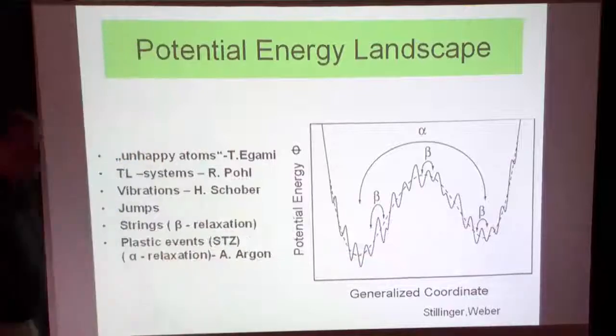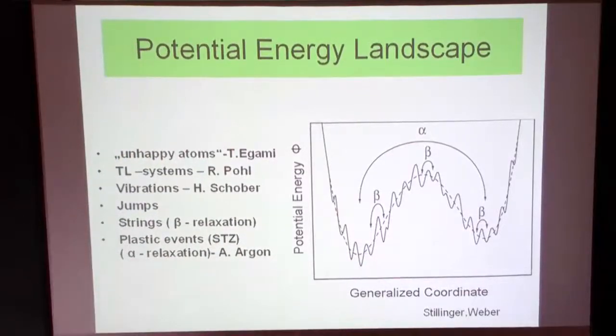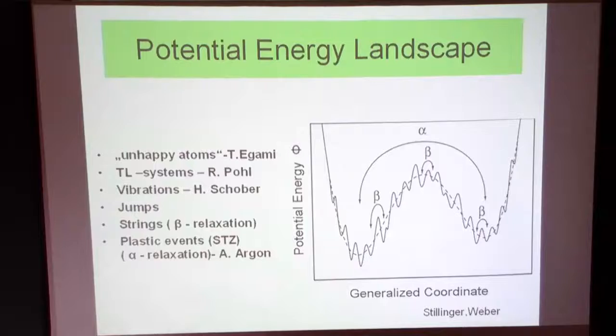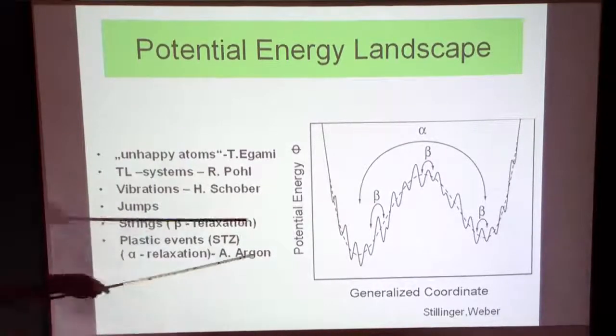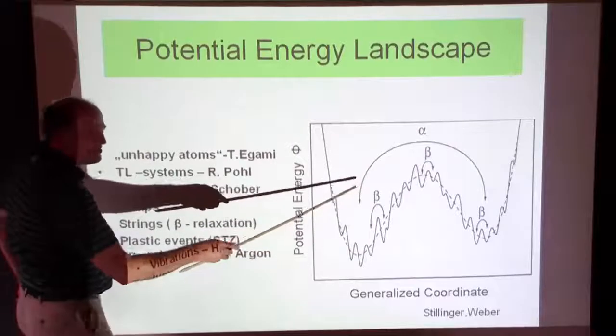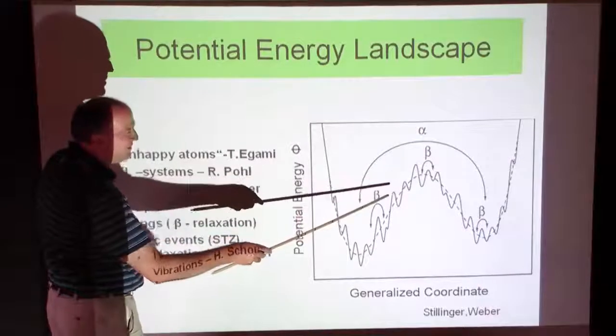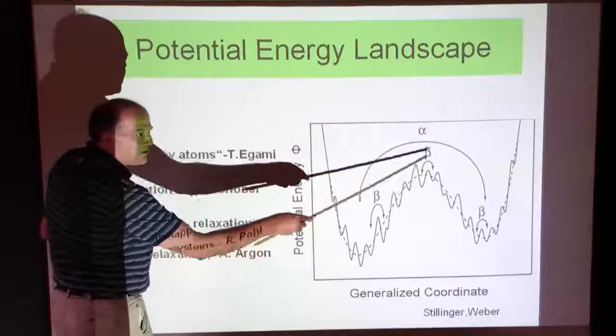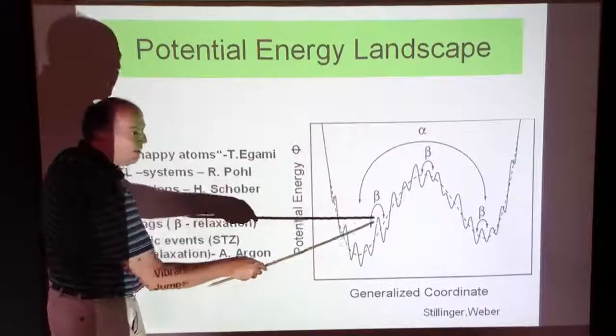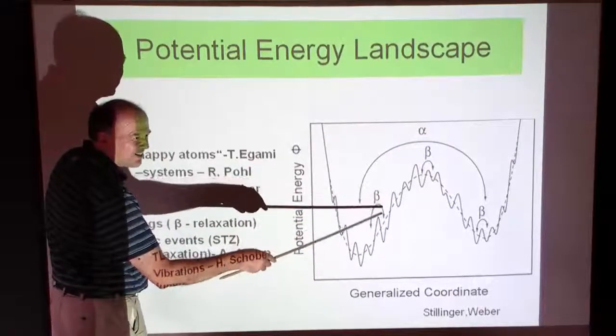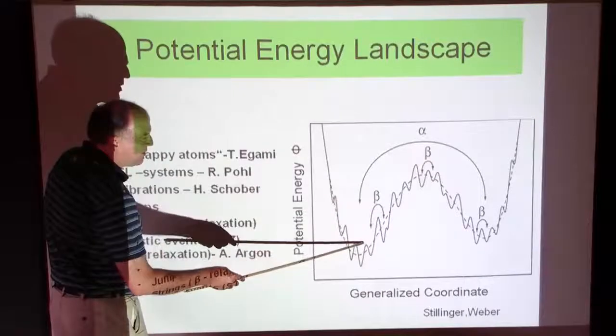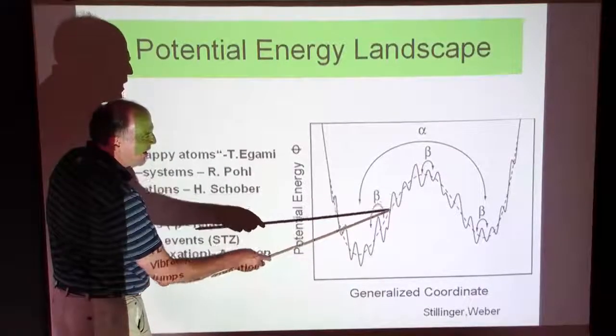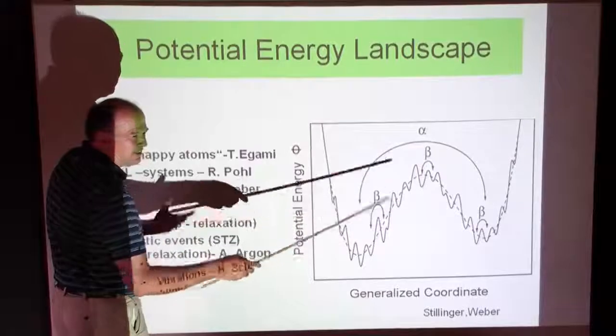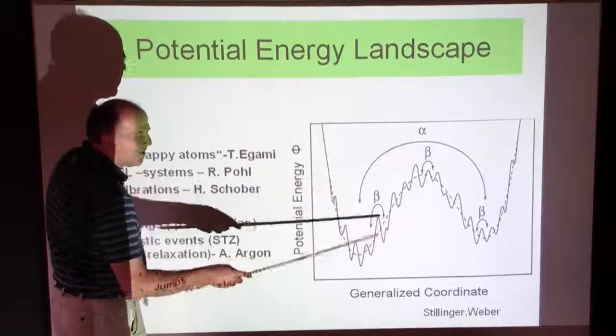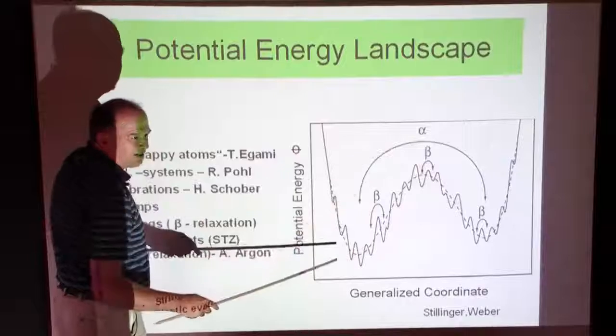I believe this. My question is, what is the difference between the small barriers, which correspond to beta relaxation, energy-wise, with the big barrier which you have here for alpha relaxation? If you discuss it this way, I will try to make a point that actually an alpha process is a composite of small beta strings. So energy-wise, you climb up to a certain moment where the local modulus gets zero, and then the system flips over into a new configuration.